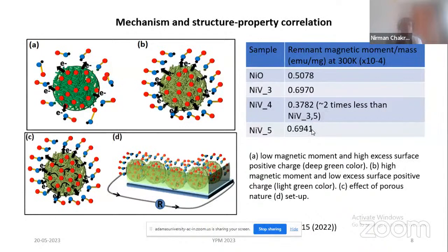So if we now compare how this has an effect on the surface behavior, NiV4 has a very flexible domain structure. First of all, it's a soft ferromagnet, and secondly, it has a lower remnant magnetic moment as compared to the other doped compositions. So when we apply an external magnetic field to this sample, the domains orient in such a way that they attract more and more nitric oxide, which is a paramagnetic species, causing maximum effective interaction. When we remove the magnetic field, since they are very flexible, they quickly reorient into their original position, and the surface desorption occurs and the system gets back to its original state.